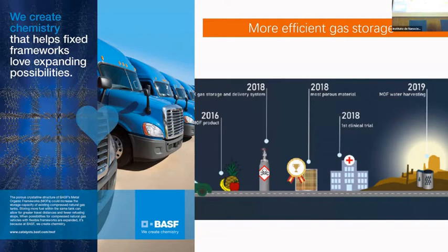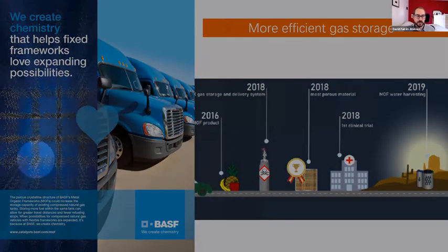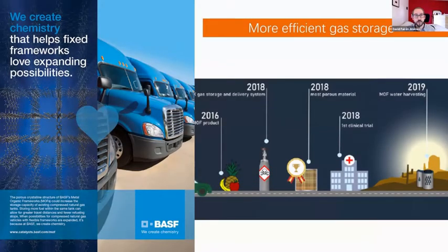They were hiring up to 30 people in a team working with metal organic frameworks. And they found later on that the materials that they were working, okay, this is from the brochure you can really find at BASF, they are still highlighting MOF5, which is a material that was not stable. So they had a lot of problems, okay? There was a lot of hype on these materials, and this really decreased the attention quite a lot when they observed it was not working.